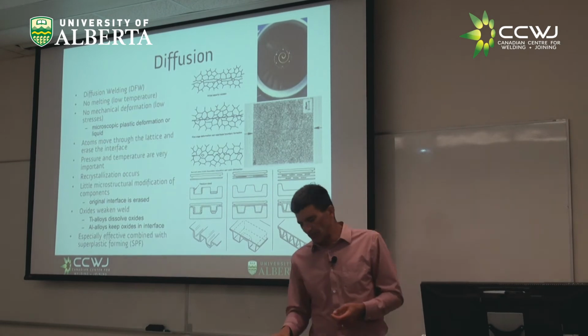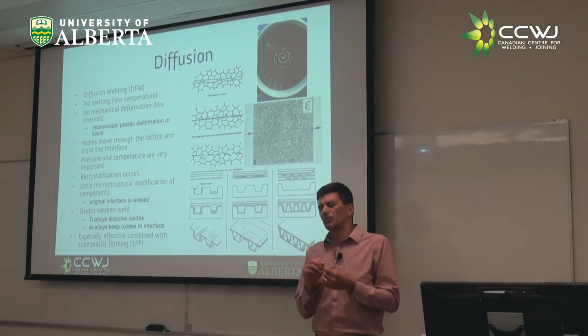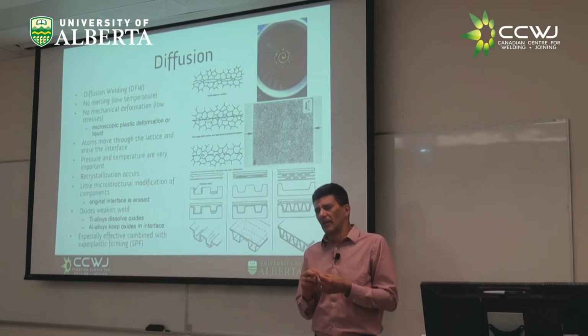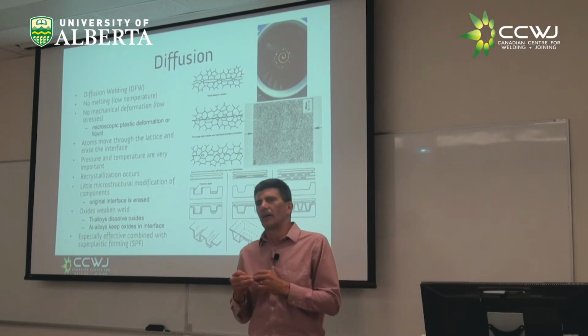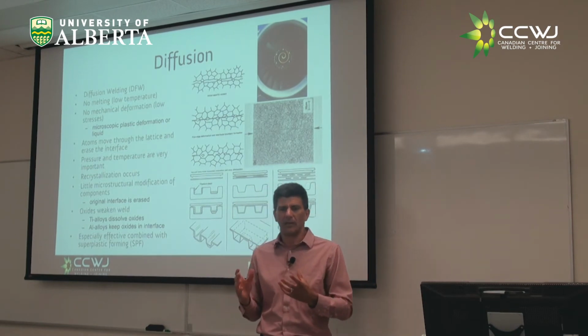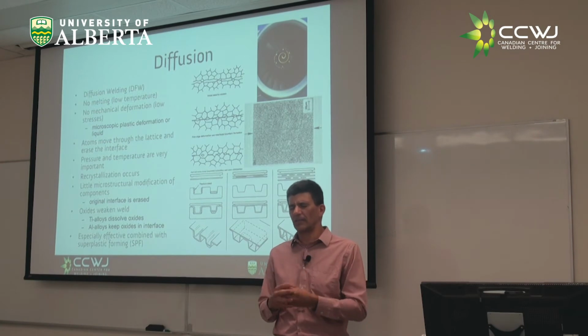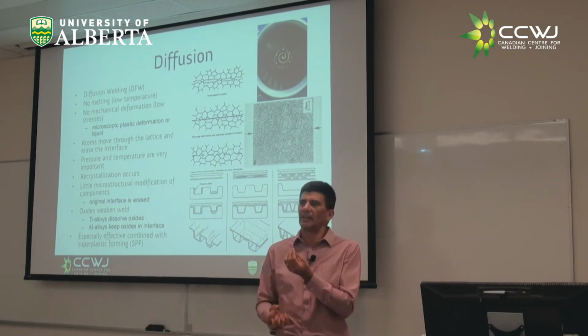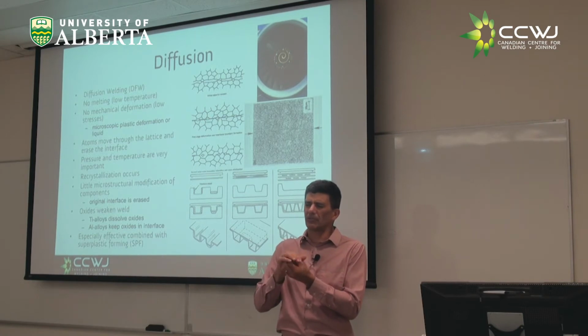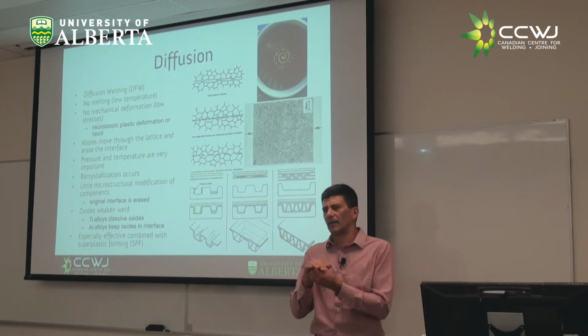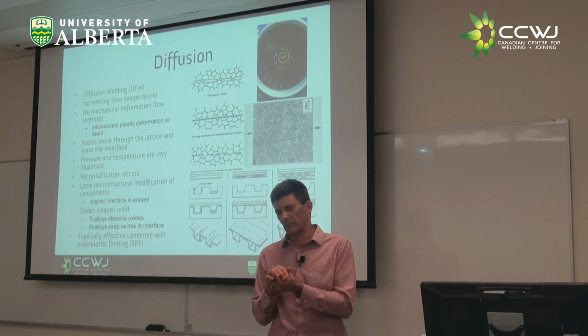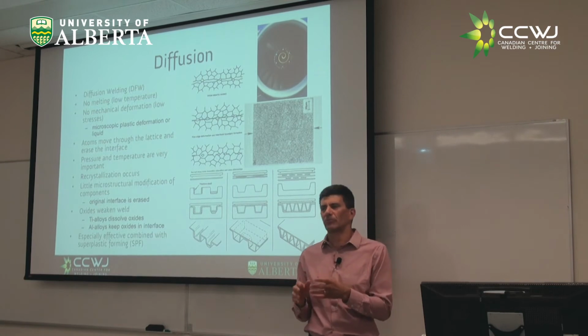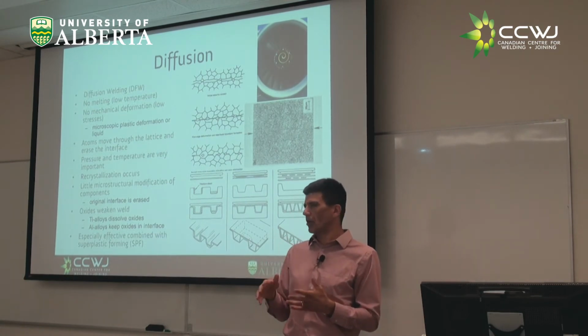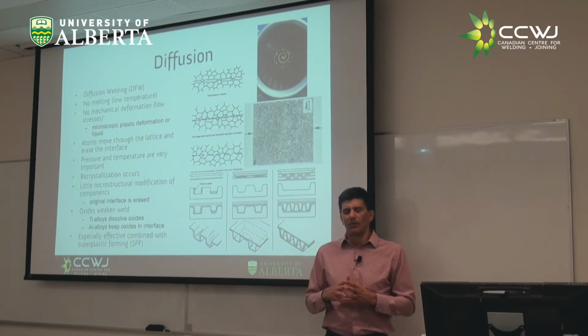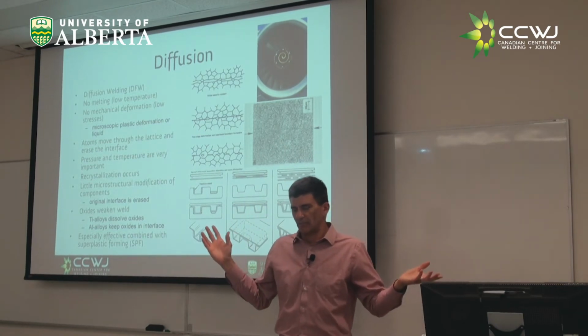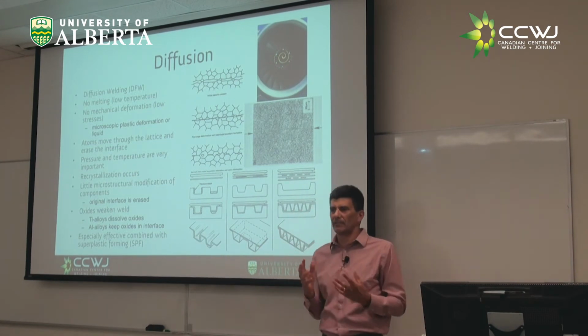This is good, but now there's something interesting. Diffusion bonding, which requires these clean surfaces, is especially good for titanium. And the reason is that titanium, unlike aluminum or stainless steel, when it gets a little bit of oxygen, sucks it in instead of having it in the surface. So the surface of titanium, if you do things right, is typically clean, right? The surface of aluminum is not clean, no matter what you do. So you very seldom are going to see diffusion bonding of aluminum, but very commonly you're going to see diffusion bonding of titanium.